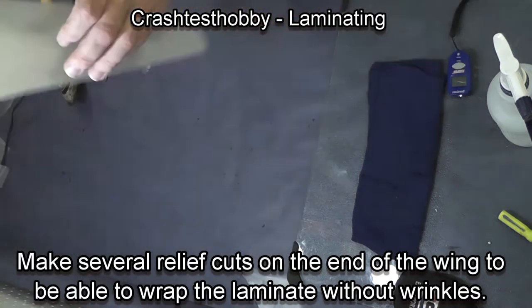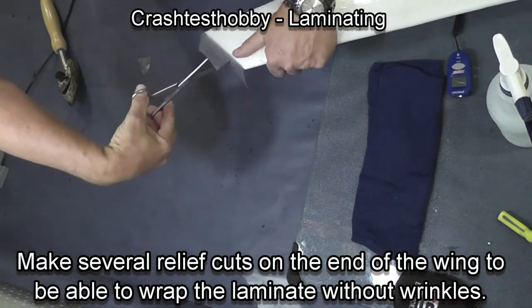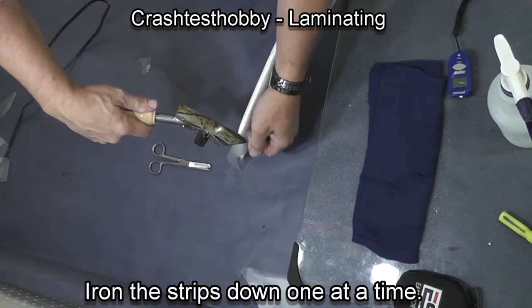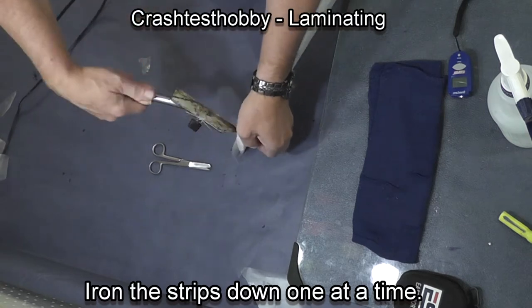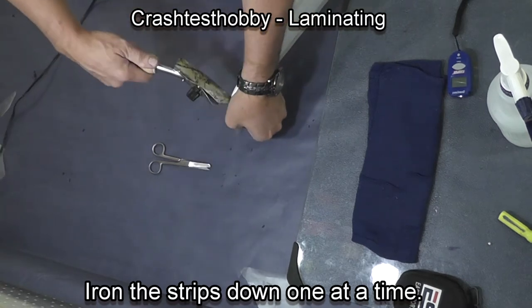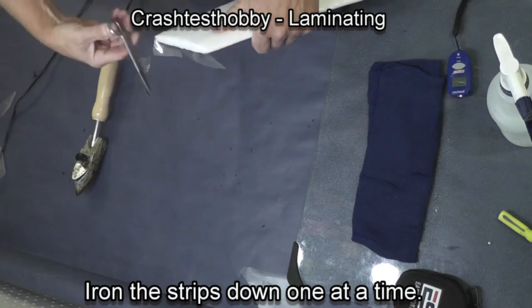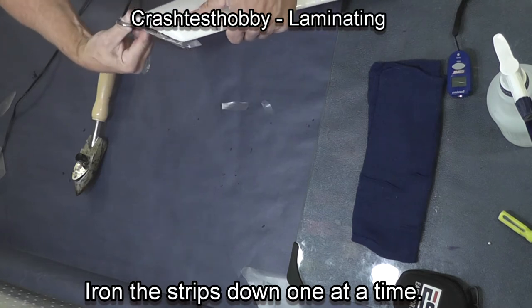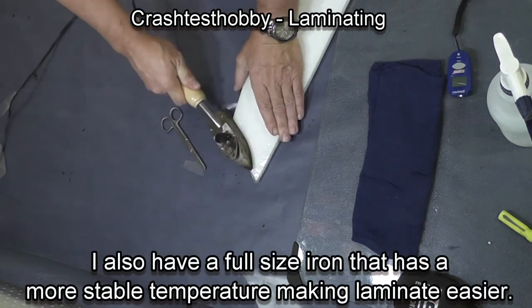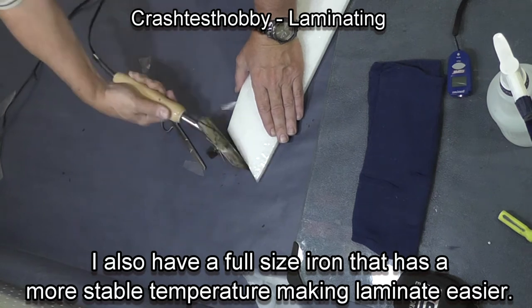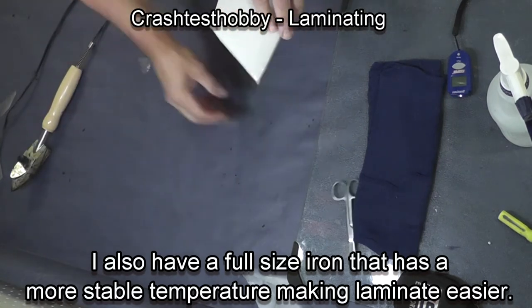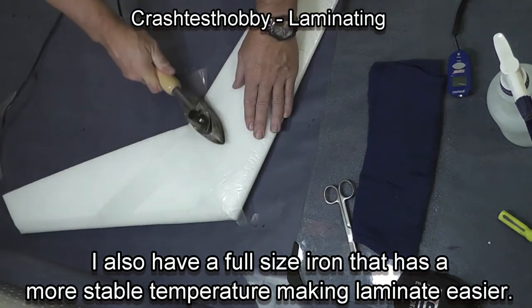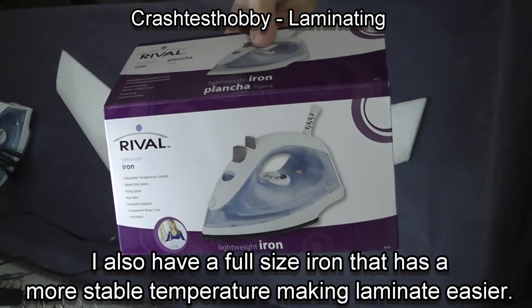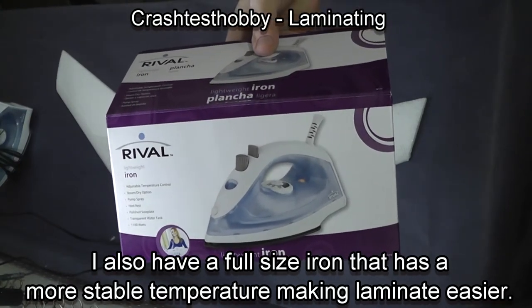What we discovered with these irons is that if they sit on the bench between use, the temperature will go up as much as 30 or 40 degrees, and the wrinkles start to form when you come back and pick it up. This is especially critical on your elevons. Now, as you noticed on the tip of the wing, I made relief cuts and wrapped the end.